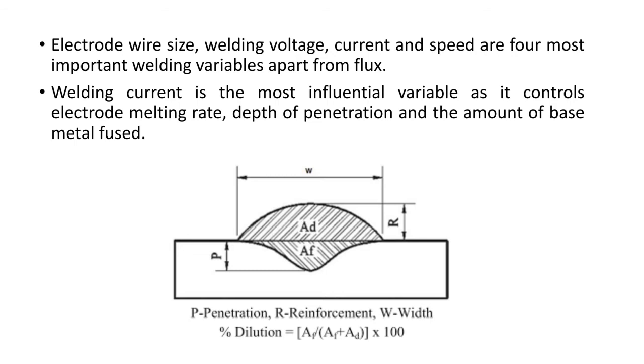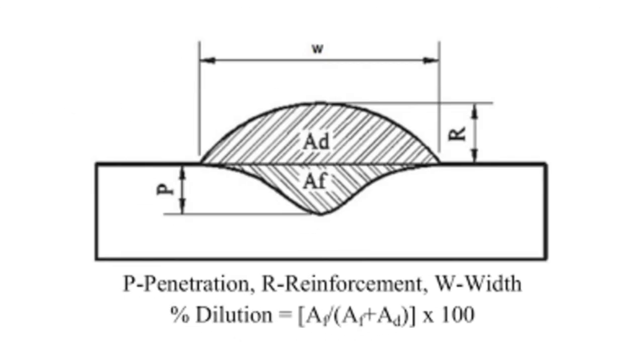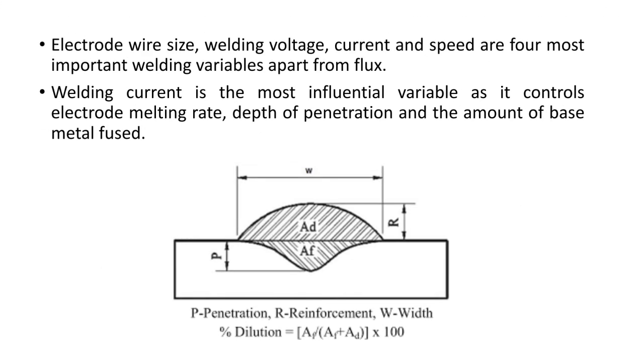Welding current is the most influential variable as it controls the electrode melting rate, depth of penetration and the amount of base metal fused. So welding current is one of the most important parameters out of these 4 because it controls the melting rate of the electrode, depth of penetration and amount of base metal fused. Here you can see the penetration is denoted by P. This is the reinforcement, and if you want to calculate the percent dilution, that is nothing but AF divided by AD plus AF into 100. That gives you percent dilution.